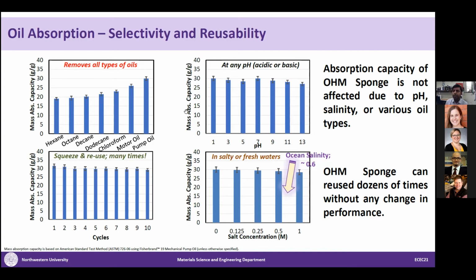Similarly, we tested this sponge for different aquatic conditions, like different pH or different salinity. For pH, we have tested water from 1 to 13, and you can see that absorption capacity does not change dramatically, as well as for salinity from 0 to 1. While the ocean salinity is 0.6 molar, we have tested up to 1, and we have seen no significant change in the mass absorption capacity there also. So it does not get affected by either pH or salinity, and it works on mostly all sorts of oils.